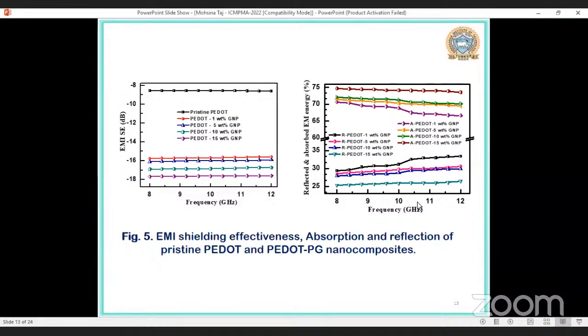We have shown here in this graph the contribution of reflection and absorption loss to the shielding effectiveness. It is observed that the contribution of absorption loss is more to the total shielding effectiveness. As we increase the concentration of conducting filler, the conducting network formed will help the motion of free charge carriers and contribute to the total shielding effectiveness in terms of absorption loss and reflection loss.